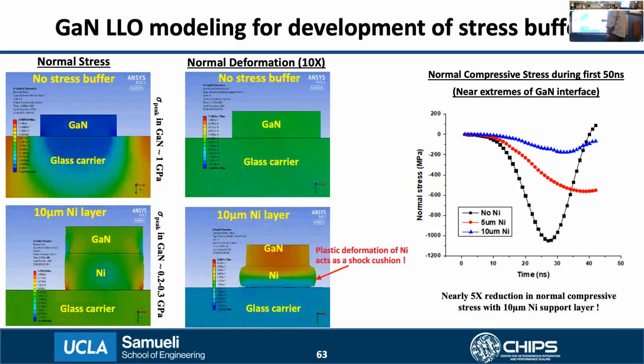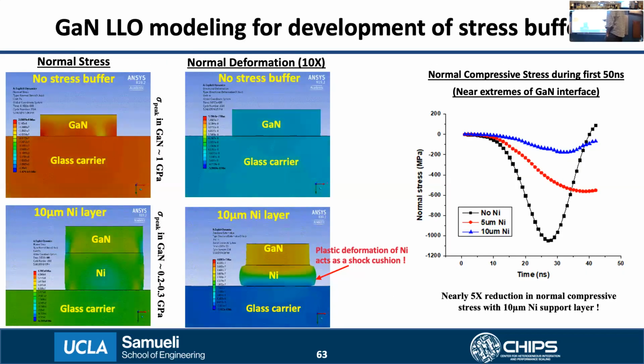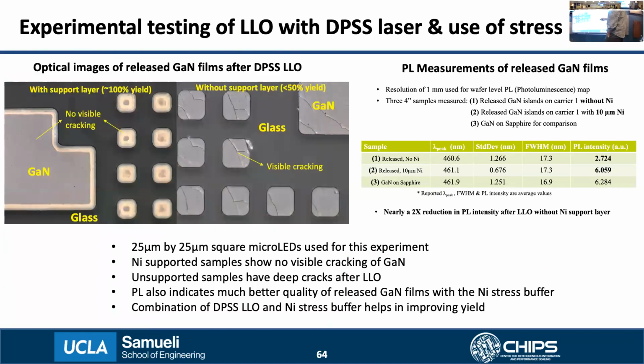To confirm the insights from this analysis, we also did experiments. Here you see a 25 by 25 micron square micro LED after performing LLO with and without the nickel. On the left side is with the nickel layer, a 10 micron nickel, where you see that the films have been released without any cracking.